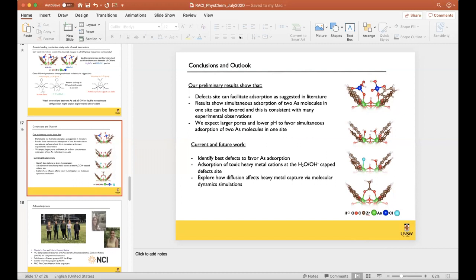So you've got your two arsenates sitting there right next to each other, and they're at a low pH and they're protonated. Certainly with phosphate, you'd expect those to condense with each other, spit out water, and you get a pyrophosphate, or in this case a pyroarsenate, where the two arsenics are linked by one of the oxygen atoms. So you'd form this cyclic system. Yeah, we haven't looked at that, but that sounds really relevant. So we might look into that.